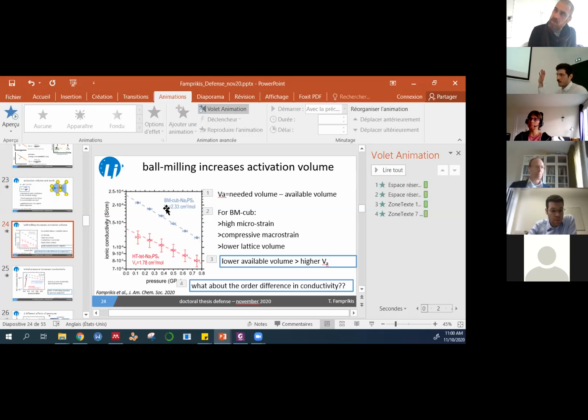But still, apart from what I've shown here, there's another approach to quantify the activation volume, in which they take, in fact, exactly what you mentioned. You identify the phonon mode that is responsible for moving the sodium ion to the bottleneck, and respectively taking it away to complete a hop. The activation volume is then the derivative, the variation of the energy of that mode as you apply pressure. So yes, it's directly related to the dynamics of the material. And I agree that intuitively, a softer material should present a lower activation volume. Okay, thanks, clear.